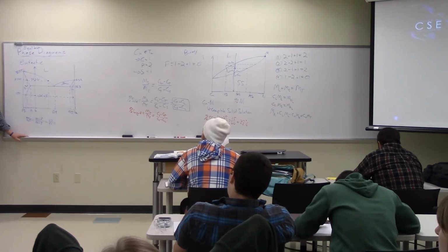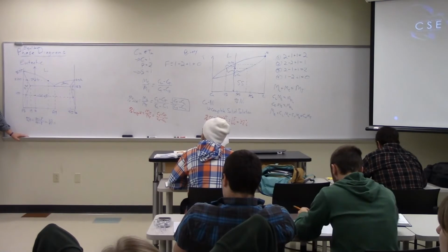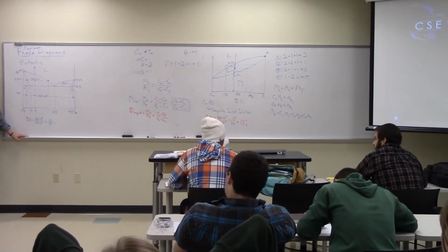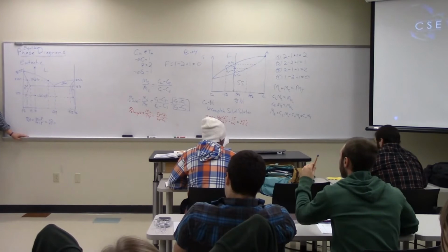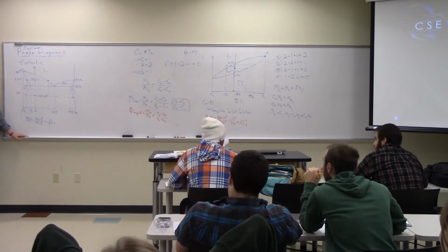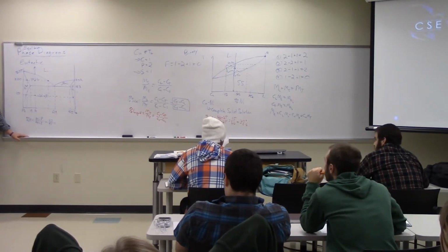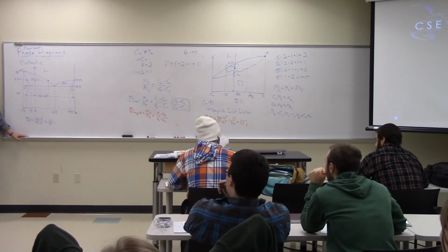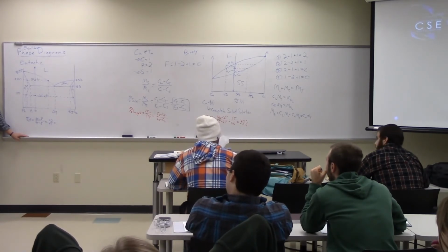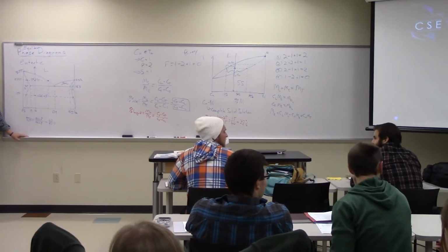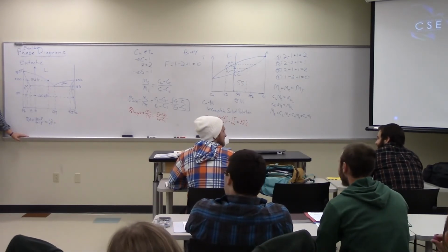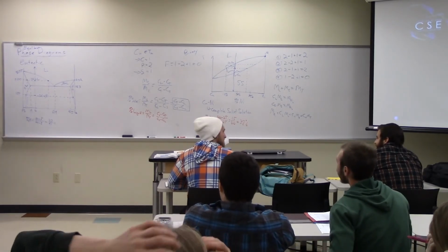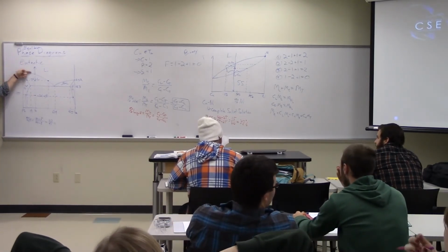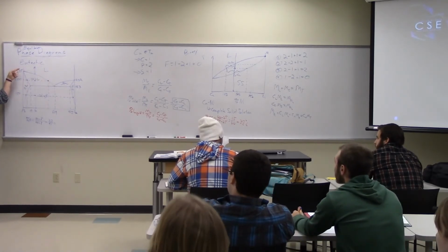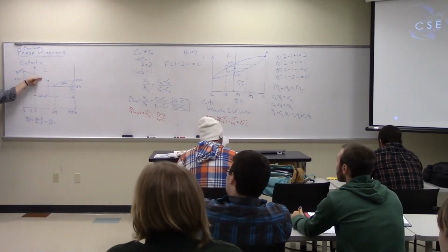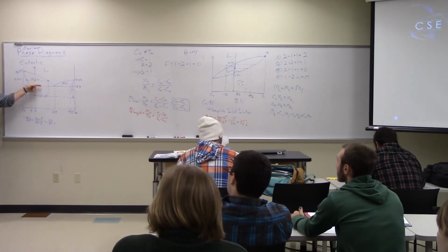Are these all empirically characterized? Yes. Okay, that seems like a lot of work. It's a painstaking process, because as I said, it's an equilibrium phase diagram, which means you have to go very slow. You've got to cool it very slowly in order to characterize it. The easiest way to characterize it is actually just to cool it down and find the liquidus line. And then this line we find because the liquid disappears. That's the instant where the liquid disappears.